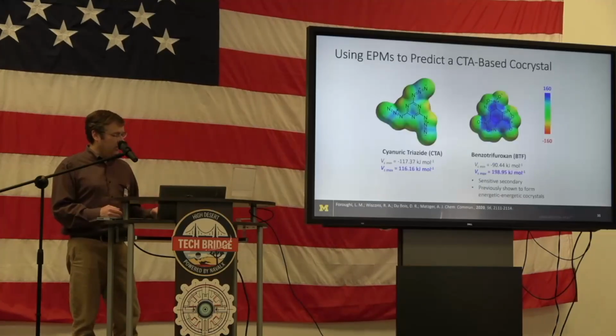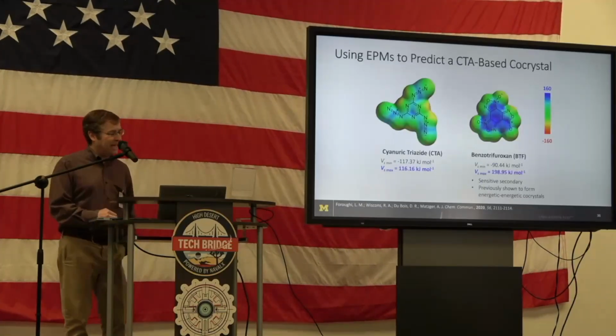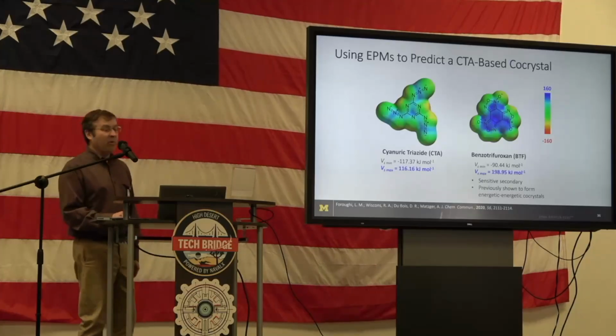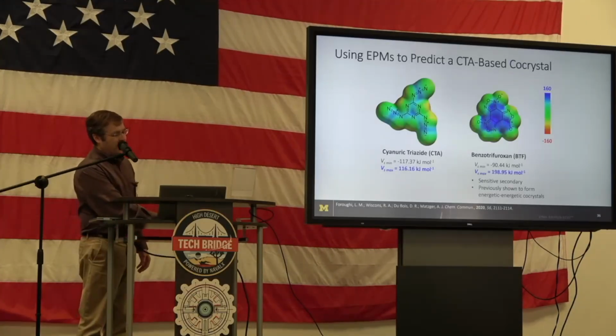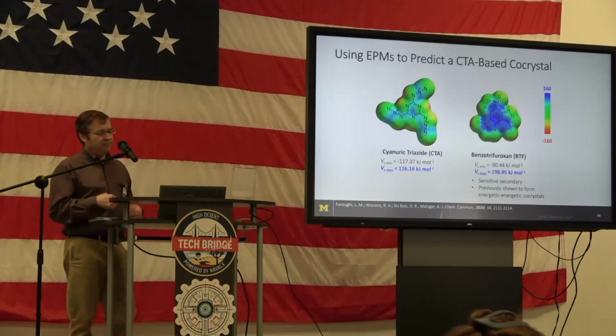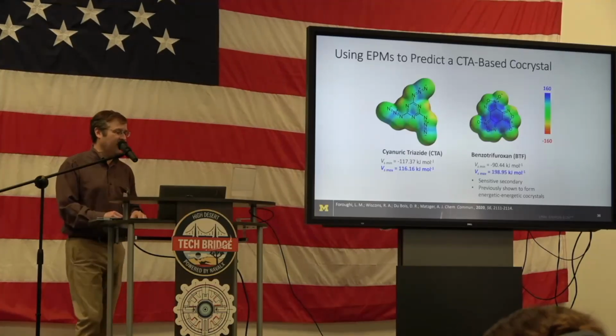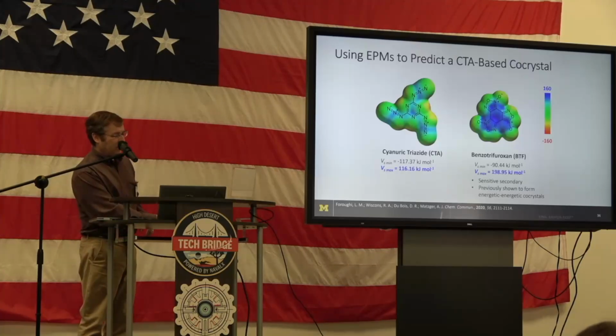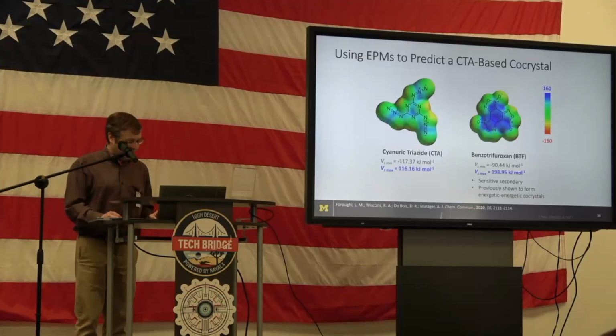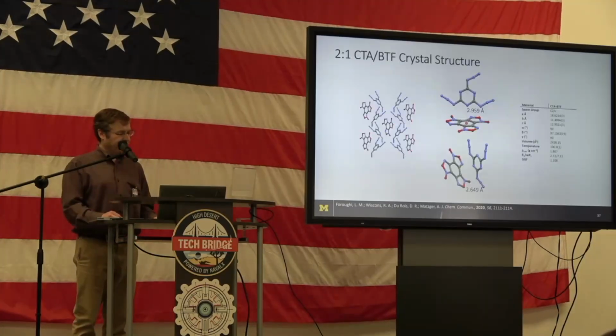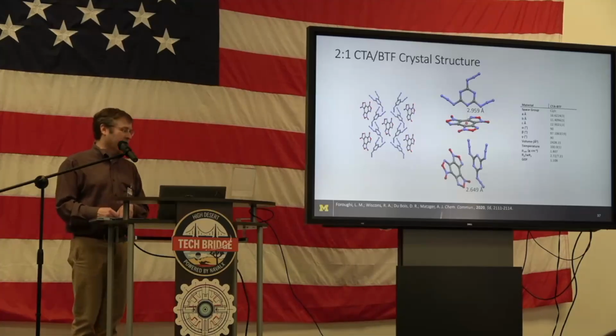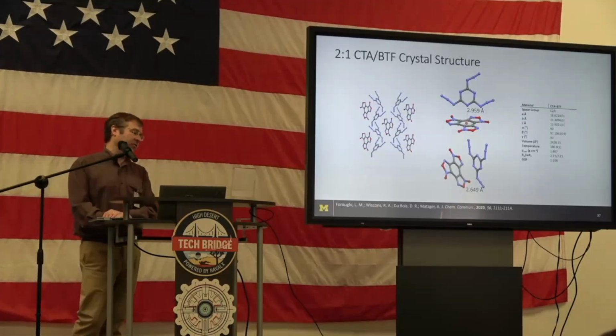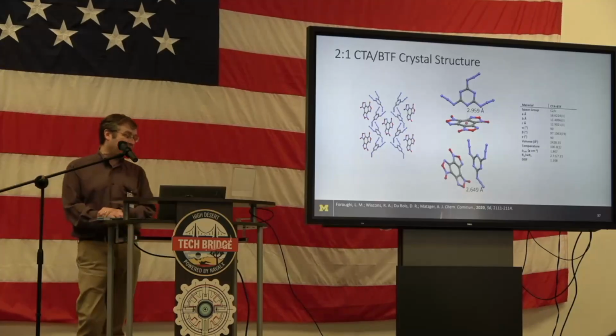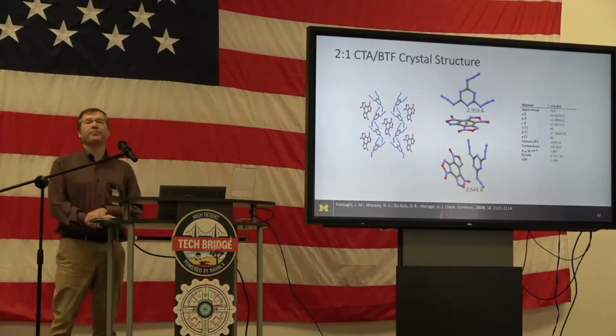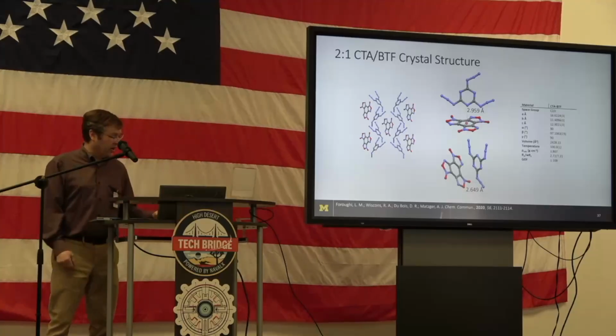And so we took it with BTF, and these are both actually fairly electrostatically neutral. There's not like a donor-acceptor interaction here that is clear to see, but this is fairly electron deficient, and we actually do have some electron donation from these nitrogens. And fortunately, it does co-crystallize, so we're able to make 2 of these cyanuric triazides to BTF, and we get a crystal structure of it. And then the question is, all right, so could this potentially be a primary?